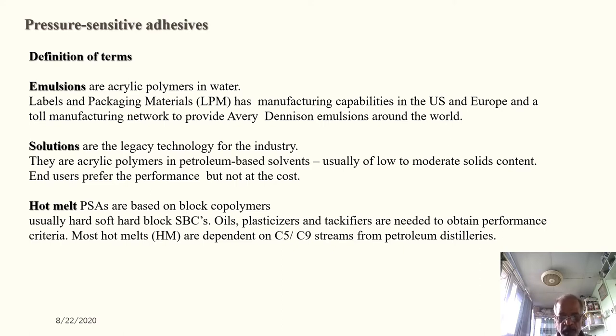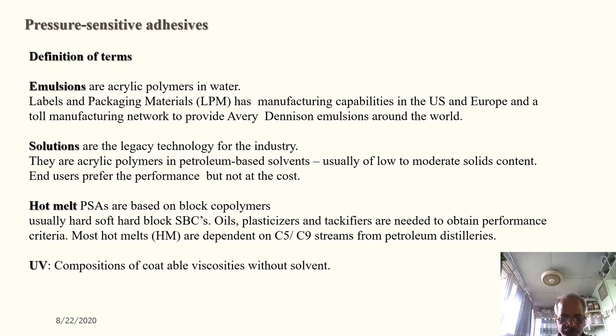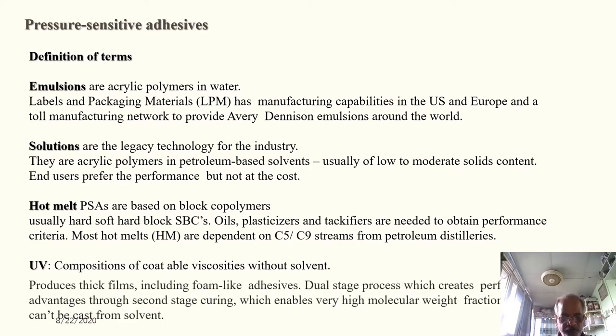Hot melt PSAs are based on block copolymers such as SBC, SIS, or SBS. Oils, plasticizers, and tackifiers are needed to obtain performance criteria. Most hot melts are dependent on C5 or C9 streams from petroleum distillate hydrocarbons. UV-cure compositions provide coatable viscosity without solvent, producing thick films including foam-like adhesives, with a dual-stage curing process enabling very high molecular weight fraction.